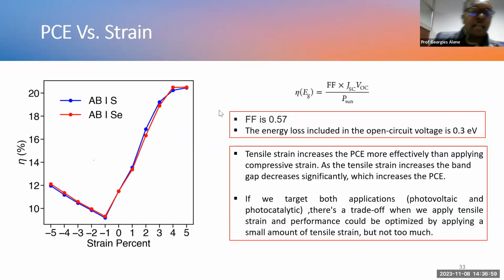In addition to photocatalytic activity, we have also investigated the power conversion efficiency for photovoltaic application. And we have calculated the power conversion efficiency at zero strain, it is around 12%. But when we apply tensile strain, as you can see, when you increase to 5%, the power conversion efficiency is significantly enhanced. So we thought that by applying strain engineering, it is possible to enhance the power conversion efficiency of the heterostructures. And it has the same trend for the two different heterostructures.